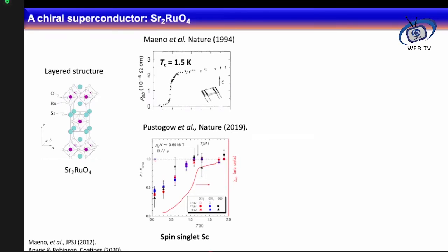Initially, people were thinking that it is a spin triplet, meaning that the Cooper pairs have spin polarization. But very recently, it was discovered that if you perform the NMR experiment to measure the electronic spin susceptibility, then in the superconducting state, the spin susceptibility is suppressed, meaning that you are losing the spin polarization. So it might be like a normal superconductor.